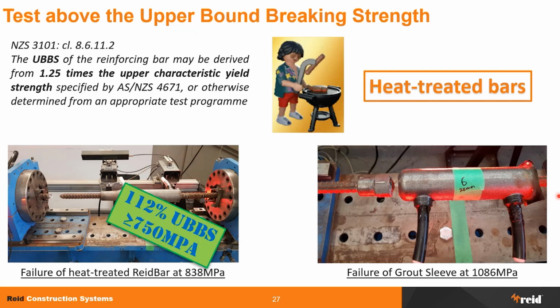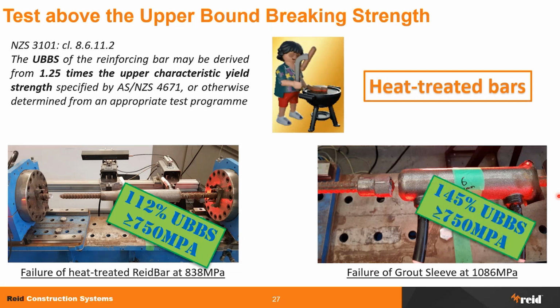And in this case, we managed to break the grout sleeve, and it happened at a stress in the bar of 1086 megapascal, which is 145% of the upper bound breaking strength, which is well above what's required. So happy days.